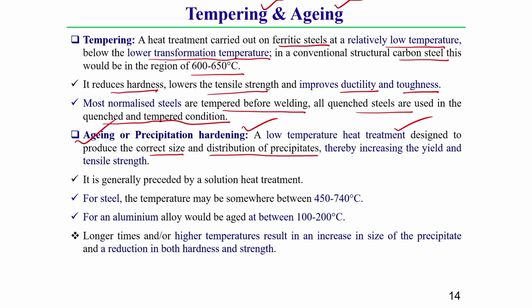So, by aging or precipitation hardening, what do we do? We produce the correct size and distribution of these precipitates. Once we do this, it increases the yield and tensile strength. So, to increase the yield and tensile strength, aging or precipitation hardening is required. This aging hardening is generally preceded by a solution heat treatment, that means it is a solution type of heat treatment process.